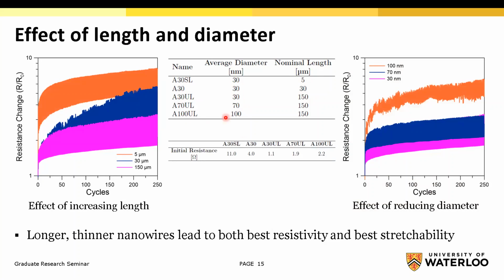You can see they have different diameters: 30, 70, and 100. And this table shows the initial resistance for all of them. Let's take a look at the effect of length first. You can see when we increase the length, this